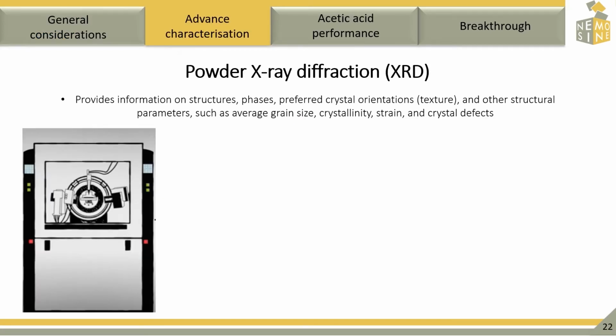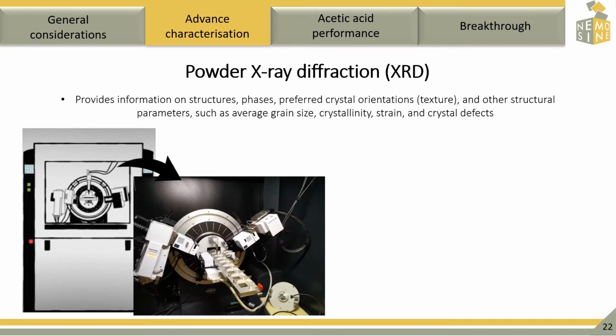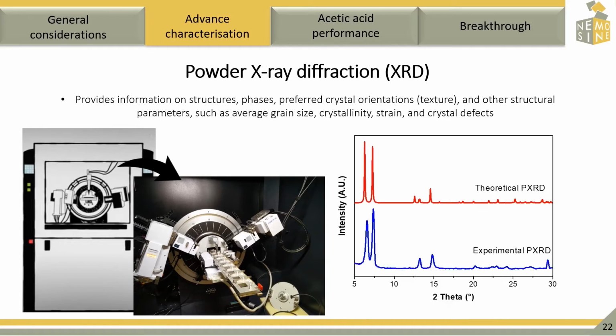One very important technique used to confirm the MOF structure is the XRD. In an XRD experiment, a sample is placed into the center of an instrument and is illuminated by a beam of X-rays. The X-ray tube and the detector move in a synchronized motion, and the signal coming from the sample is recorded and graphed, where the peaks related to the atomic structure can then be observed. This technique reveals information about the purity of our materials, and the pattern is considered a fingerprint of the MOF.